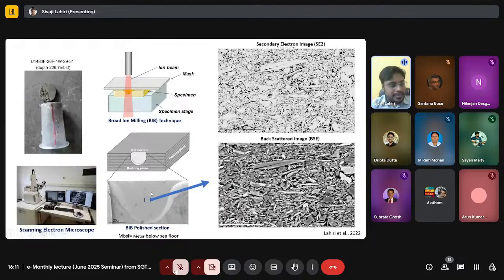So if we utilize this technique, we can prepare sample surfaces with undulation less than 5 nanometer. So very smooth sample surfaces. After that, we tried to capture images of the sample surfaces using scanning electron microscopy. So here you can see this is the typical secondary electron image of this particular sample, and this is the backscattered electron image corresponding to the same sample of the same surface area.